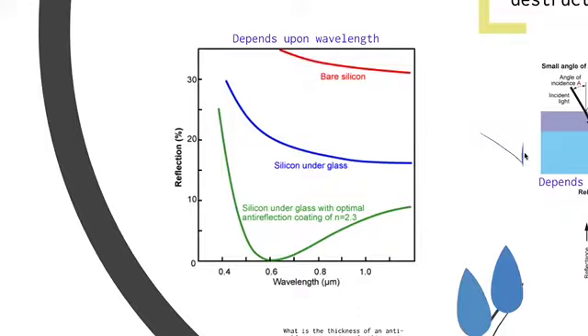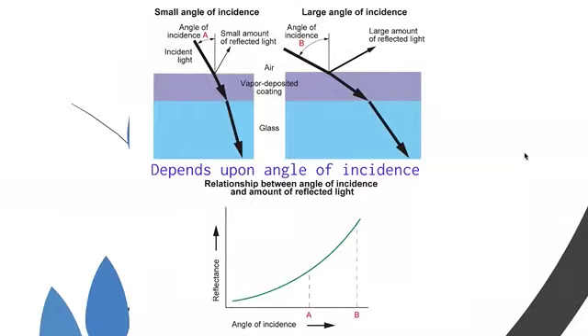So the consequence is that the thickness is not general. It only works for one wavelength, one angle. I designed my coating to be perfect at 0.6 microns. If I change my color a little bit, it no longer works. That's silicon in glass with optimal anti-reflection. It also depends on angle. By the way, if you don't use any anti-reflection coating, the reflection is huge. This is for silicon, which as we know looks like a mirror. Most of the light is reflected because of the high refractive index. With a small angle there's a small amount of reflected light; with a large angle, more light is reflected.